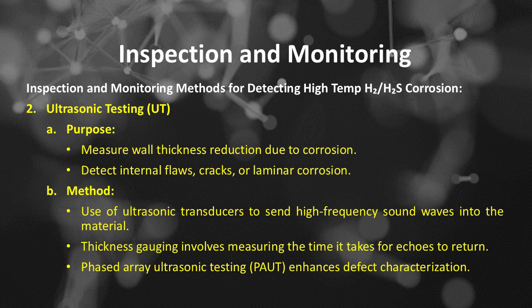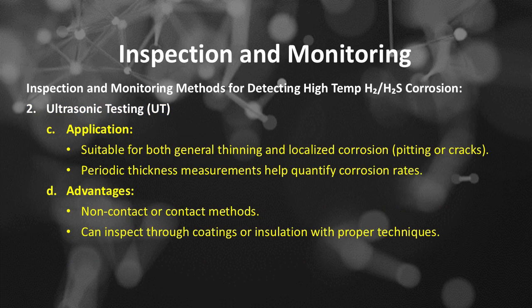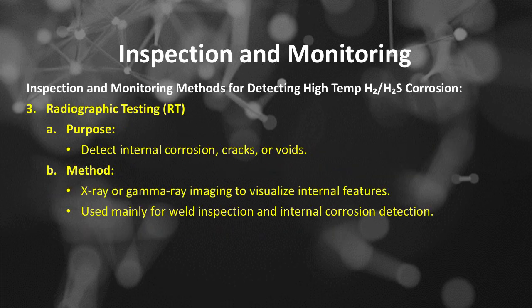Phased array ultrasonic testing, PAUT, enhances defect characterization. The applications of ultrasonic testing include: suitable for both general thinning and localized corrosion, pitting or cracks. Periodic thickness measurements help quantify corrosion rates. The advantages of ultrasonic testing include: non-contact or contact methods, can inspect through coatings or insulation with proper techniques.